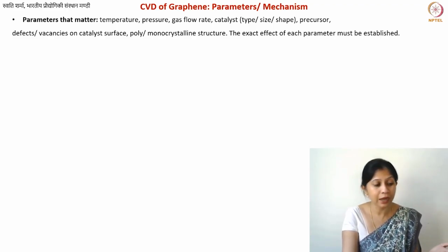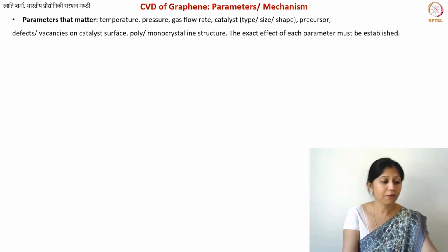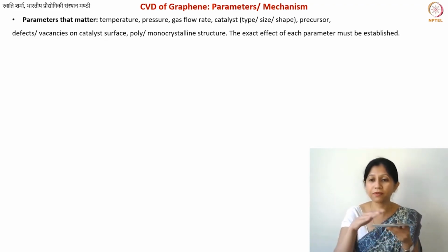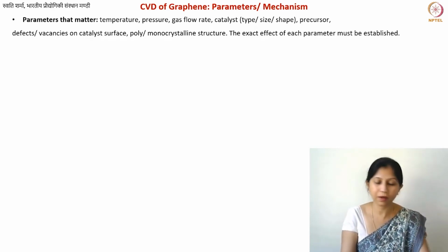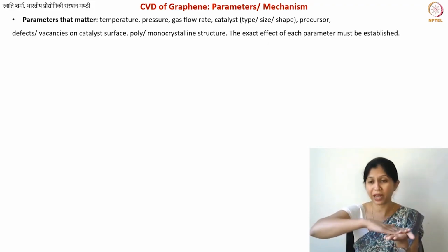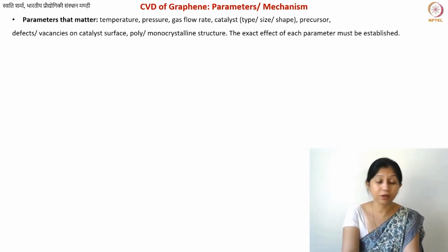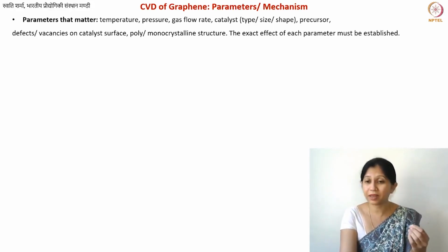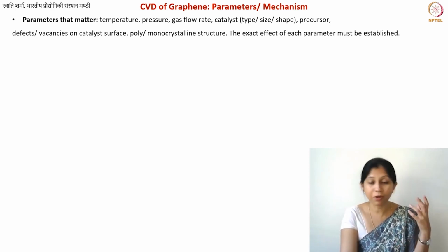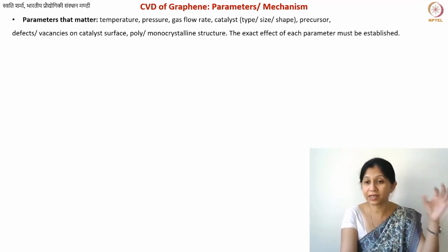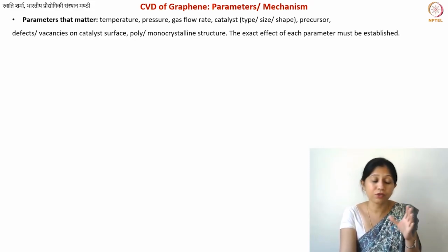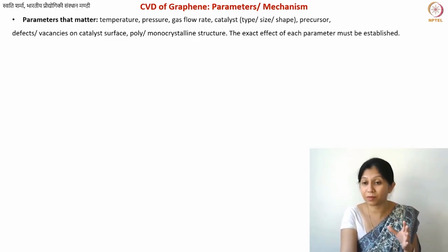In most cases, when graphene is produced on these metal substrates, what do you do after that? You often transfer the film. So I grow the film here and I transfer it onto another substrate, and that transferring can be done simply by adhesion and peeling off. But because often the substrates, the catalysts, are transition metals, they can be etched with acids. So you can also perform the etching processes in order to remove your graphene layers and transfer them on top of another substrate that is the desirable substrate for you.